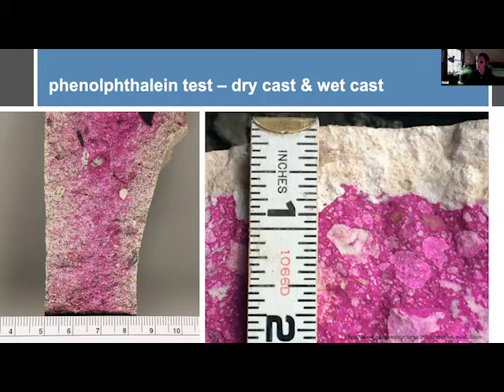The block on the left is our dry cast. On the right is some wet cast concrete. The rate of carbonation in wet cast is slow, averaging about 4 millimeters per year, and it slows down with age. The wet cast on the right is somewhere around 6 years old, and carbonation is shown only at the outer crust of the concrete.